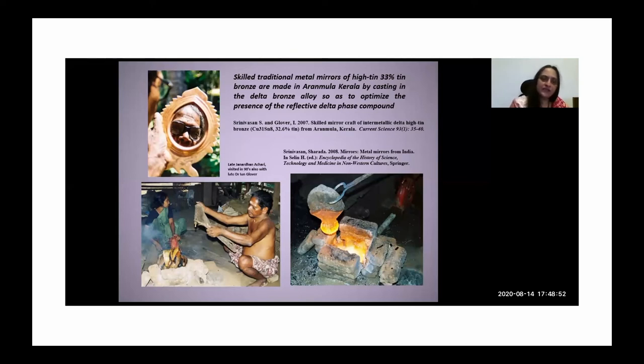So here you see Janardhan Achari, who's firing the mold in this hearth, which has been covered with coconut husks and things like that. And why I call it a crucible cum mold is because it's a closed crucible, so that there are no oxidation losses. What you saw when I was pointing to Swami Malay was the mold faces up and the metal is poured in. But here it's a closed crucible, so that inherently there's no oxidation losses. And when it's tipped over, it just flows in, so that it doesn't have any chance of getting impurities due to oxidation and such like.